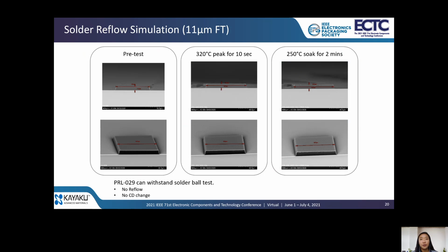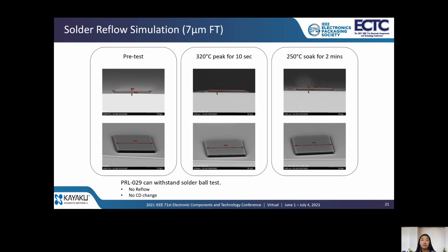Additionally, a solder reflow check was completed in-house to ensure no failure mechanisms occurred, such as cracking, delamination, or critical dimension changes during the simulation. 100 micron by 100 micron pillar samples at 10 or 11 micron and 7 micron film thicknesses were cured at 200 degrees C for an hour under nitrogen. The samples were then exposed to a 320 degrees C peak for 10 seconds, followed by 250 degrees C soak for 2 minutes. And we were able to take SEM images between each step. So here's a film at around 10 micron without any cracking or delamination or CD changes. And then here is the film at 7 micron, also without any failure mechanisms. So overall, PRL29 was able to withstand a simulated solder reflow test.